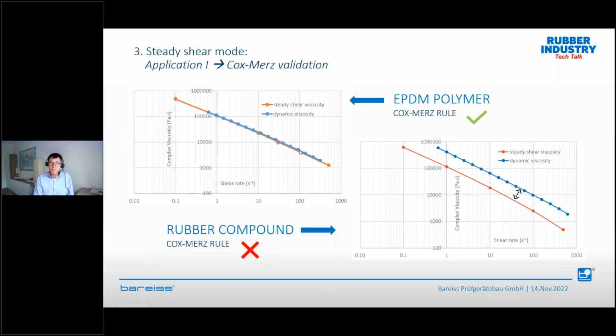Does it work? Yes, it does. So we compared it. On the left side, we used a very easy linear polymer. And then we ran a dynamic viscosity test, which is here the blue line. And we ran the steady shear viscosity test, what I mentioned before, with these different shear rates, with these different speeds. And because of the Cox-Merz rule, because it's a linear polymer, both should be on the same curve. And it is, so it works perfectly, our RPA Ultra.